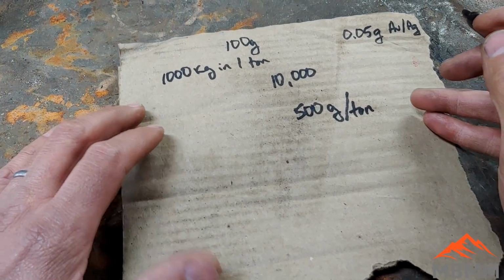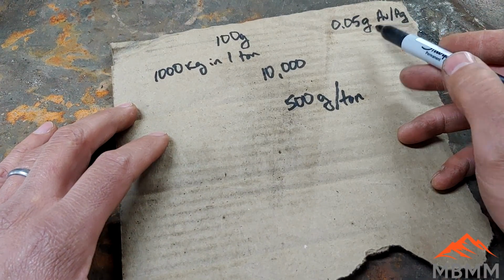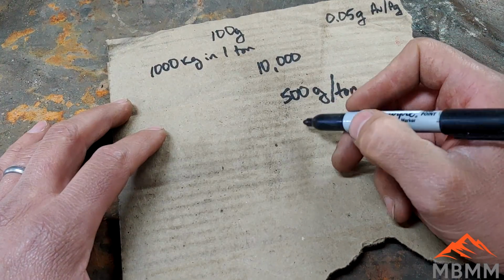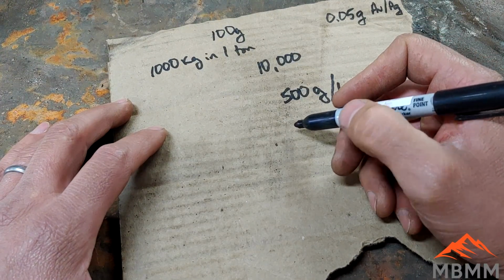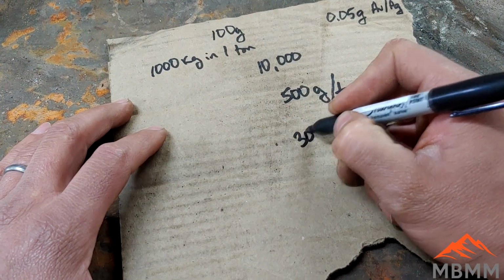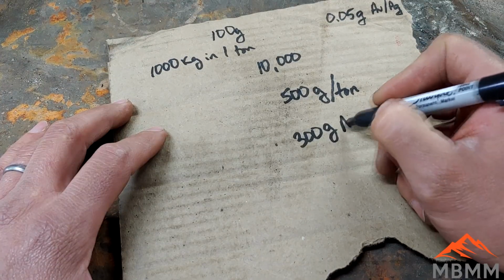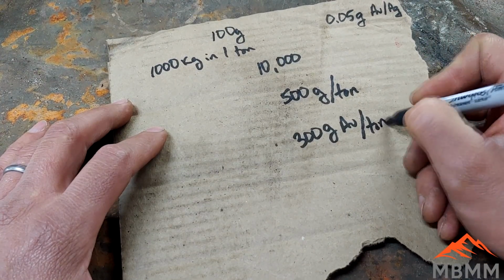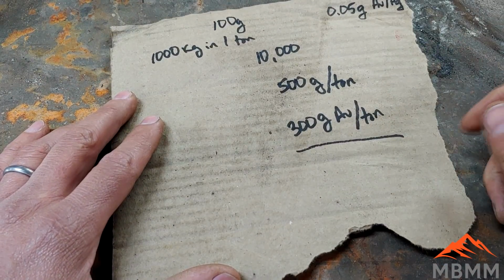per metric ton. And we figured, judging by that color of the bead, it was about, let's call it 3/5. So we're going to say there was 300 grams of Au per ton. So that's not too bad. All right, so let's talk a little bit about what we figured out. So we found out that in the first one, we didn't have enough basic flux. And so I added twice as much flux to the second round with lead, and that's where we ended up with our 0.05 gram bead.